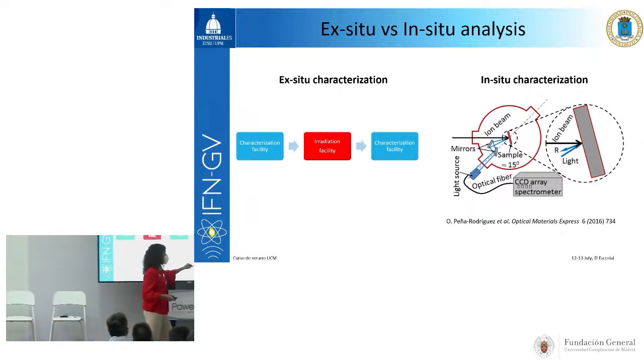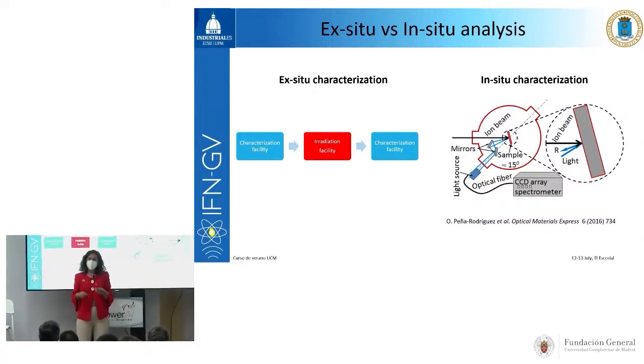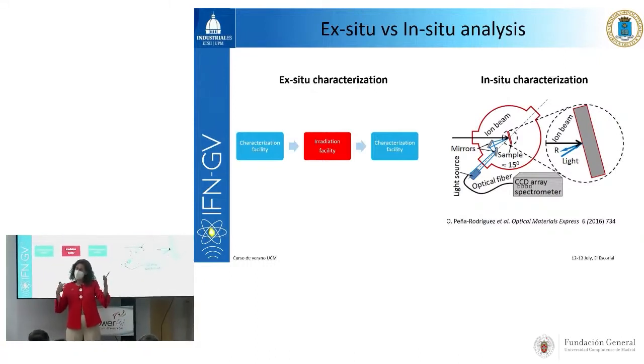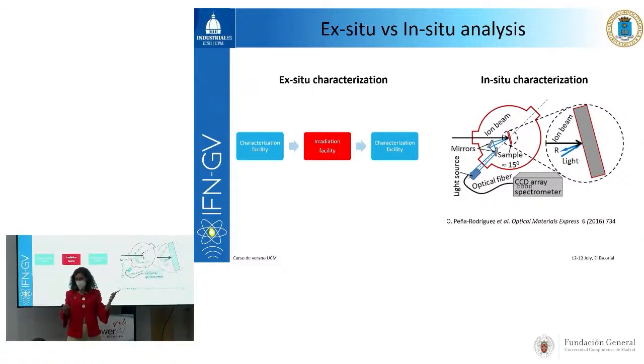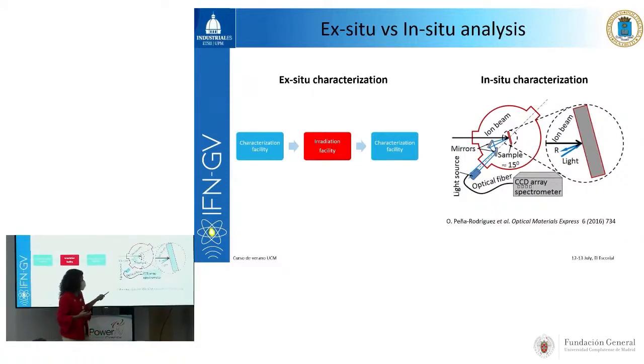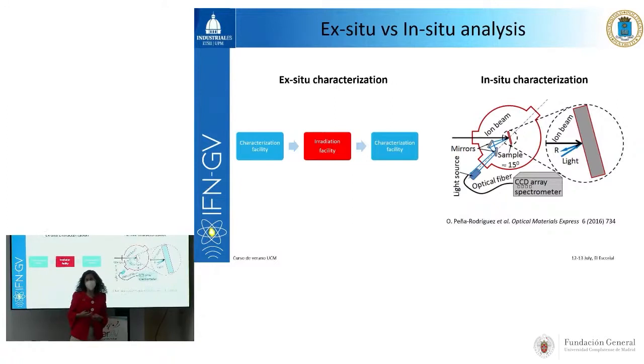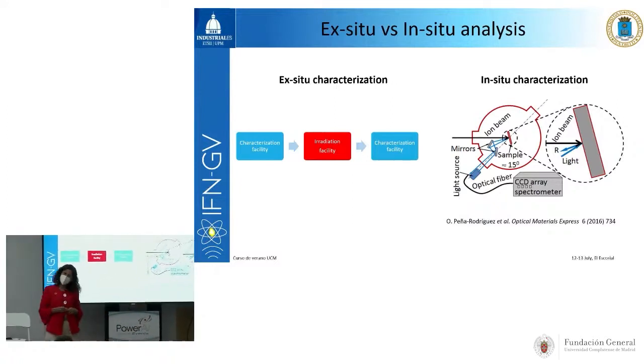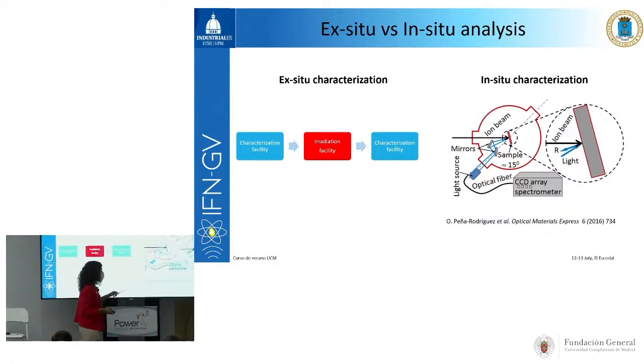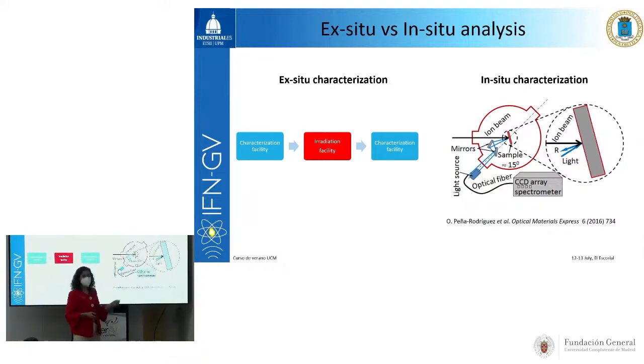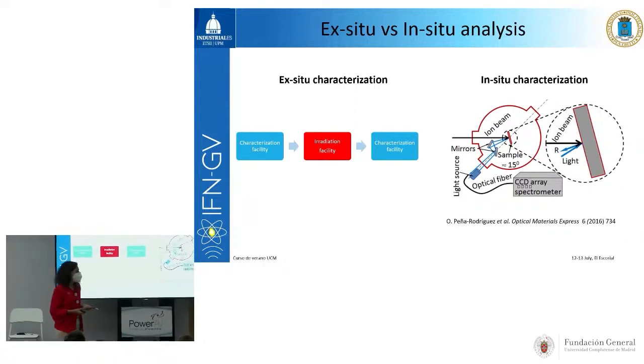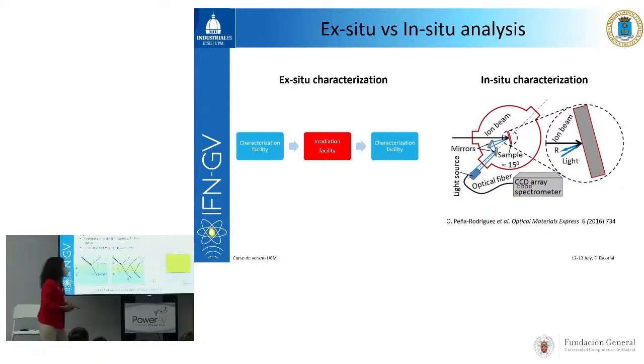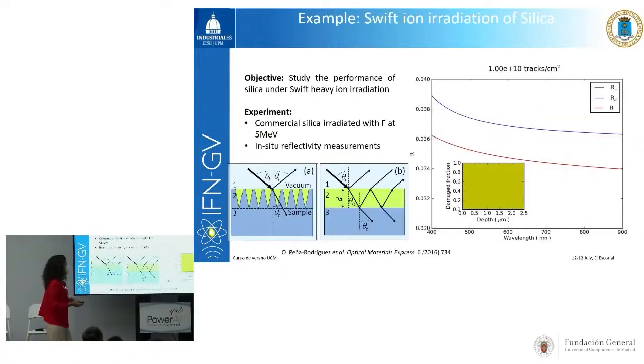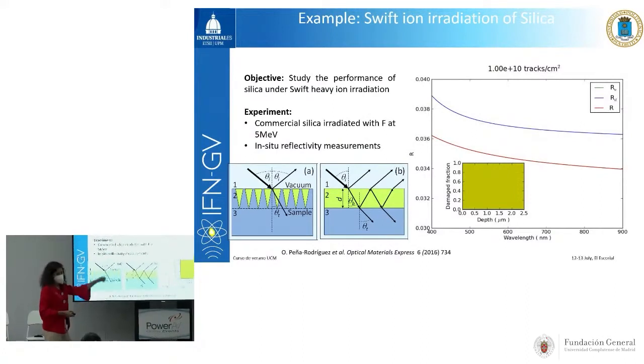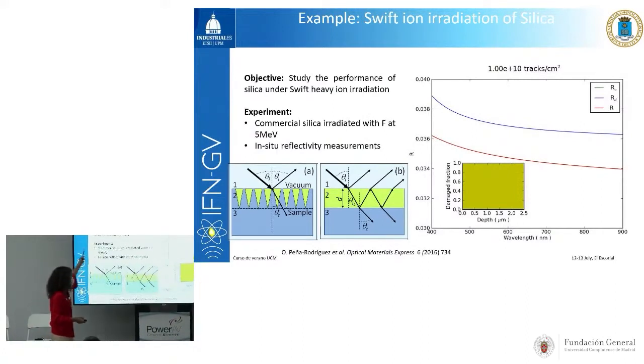Whereas if we carry out in situ characterization, that means that we are characterizing the sample during irradiation, when being irradiated. And this was a setup developed by Ovidio Peña, who belongs to our research group. Basically, this is to measure the optical properties of the sample when being irradiated with ions. In this particular case, this is one experiment, which is in situ characterization.